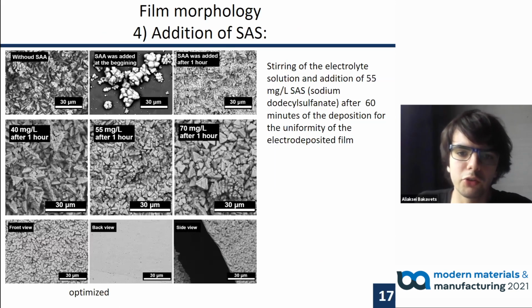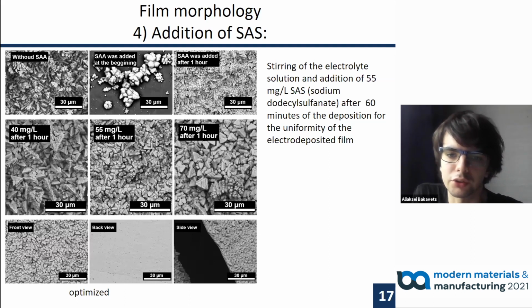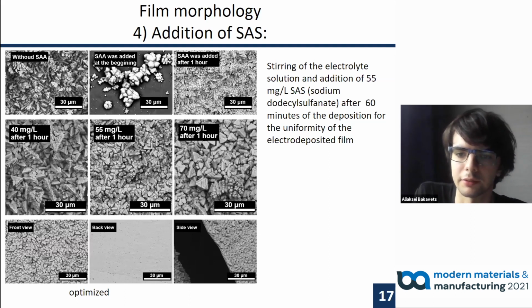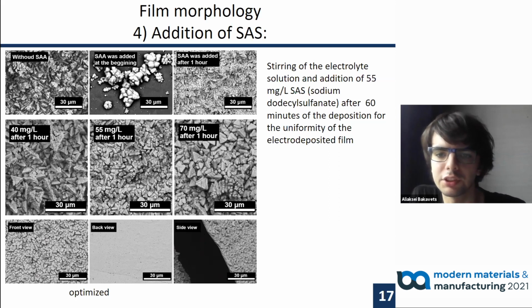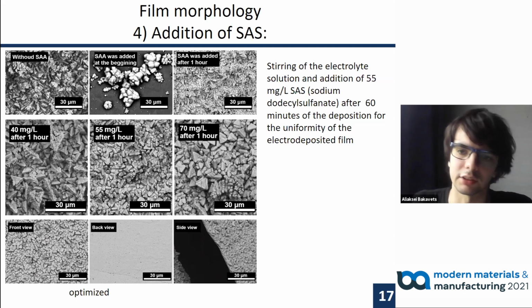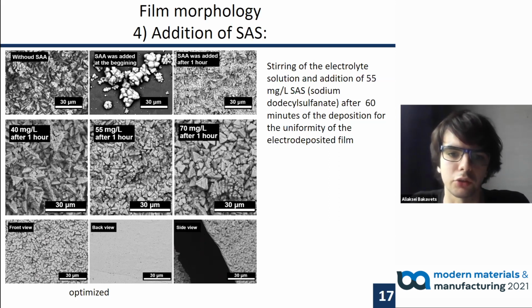To avoid non-uniform electrodeposition, the solution also has to be stirred and the surface active substance has to be added 60 minutes after the beginning of the electrodeposition. The time of the addition is important as surface active substance prevents nucleation of bismuth telluride if added at too early a stage.